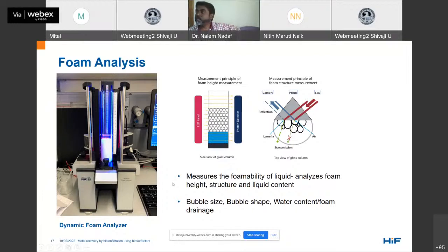So we did the foam analysis experiments using a dynamic foam analyzer instrument, where the foam is generated in a glass cylindrical column, which has a diameter of around 40 millimeter, and the foam is generated by sparging the air through a frit, which is usually a P3 glass frit, which is placed at the bottom of this glass cylinder, and air is sparged through it at the rate of 0.2 liter per minute. And we foam this solution for around 50 seconds, and we measure the stability of this foam for around 5 minutes.